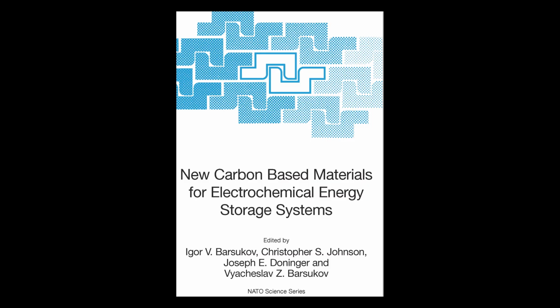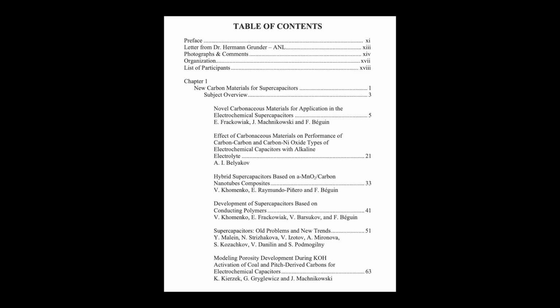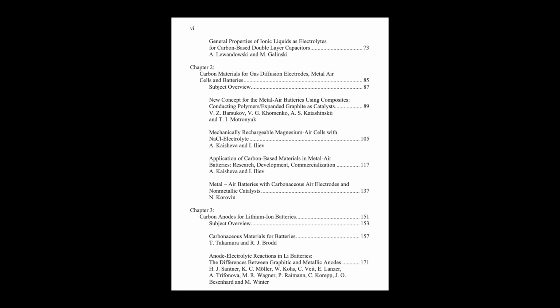Still in supercaps, but looking at manganese oxide, MnO2. Not carbon, but uses carbon, right? Exactly. They discussed using amorphous, hydrated manganese oxide prepared by chemical co-precipitation. And the key finding here was about the carbon additive used with it. What did they find? Adding carbon nanotubes, specifically multi-walled CNTs, gave a significant performance improvement compared to just using regular carbon black.